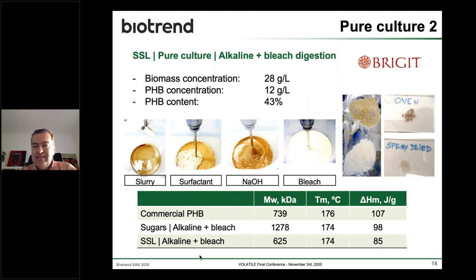And you can see on the right-hand side the slides showing different materials, which were processed in the exact same way, but dried differently. On the top, the yellow powder was dried in an oven. The white powder was dried in a spray dryer, which immediately shows us that the residence time is very important in relation to the browning of the end material. But we don't expect our polymer to become brown, so all that browning is indeed caused by impurities. And when we try to melt the polymer, the material that was oven dried doesn't melt at all. The one which was spray dried melts a little bit, but there's still some granularity and color, which indicates that the purity was not perfect.